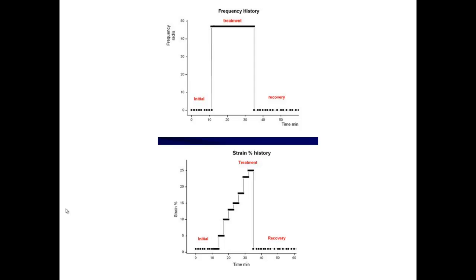And now in step 2, we are doing two things. We are going to shear thin the melt, so increase the frequency. Here you see that as a step function we go up to 47 radians per second, and at the same time I am increasing every 2 minutes. I am increasing stepwise from 5% strain up to 25% strain, in this case the strain percent, and then I am studying the recovery curve. In other words, I'm going back to the initial conditions just to see what happens to the melt.